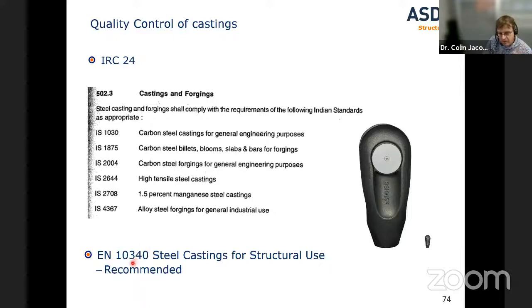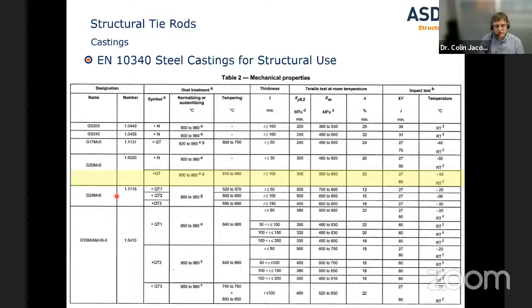So in the Eurocodes, they have a specific casting standard just for structural use, just for use in structures designed according to EC3. Now, a typical grade we will use is G20Mn5. Typically, it gives us a yield stress of about 300 and an ultimate of 500 to 650. But more importantly, it has good elongation at 22% and very good Charpy values. So it's a quench and tempered steel, but this is generally one of the more practical steels to be using for this type of structure.